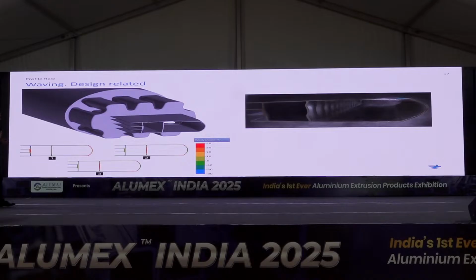If we analyze the velocity deviation during the cold process, we can see that at the second and third stage, which refer to the middle stage and end stage of the extrusion, there is a tremendous effect on the velocity. This central wall starts to flow faster and faster, which can also be checked by the change of the temperature field, which you can see here. Or, if we look into the graphs, you can see that the central point starts to be faster and faster somewhere around the middle stage. This is exactly when these defects start to appear.